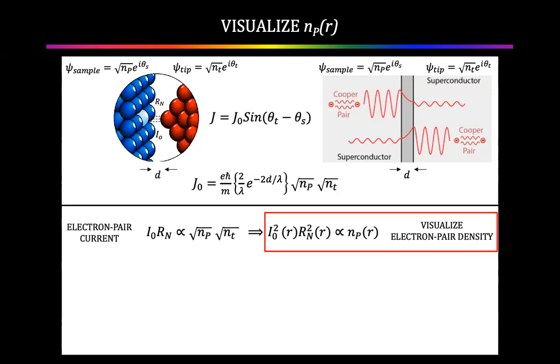It's an open question about how to deal with an S-wave tip on a complicated superconductor. That is not a solved problem. But actually, do you see anything when it's an S-wave tip on the D-wave? Well, you know, there's no such thing as a perfect tetragonal crystal. Sure. That means the point group symmetry of the Cooper pair is not perfect. That means there's always some overlap with the wave function. But in detail, that's not a solved problem. Like in YBCO, it's so orthorhombic that we would guess there has to be a big S-wave component.